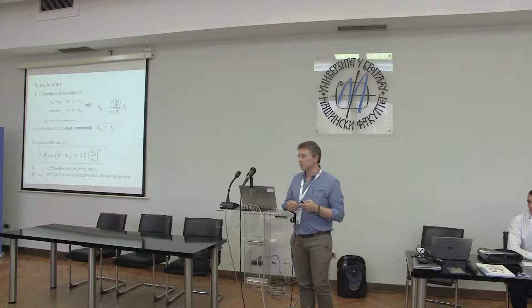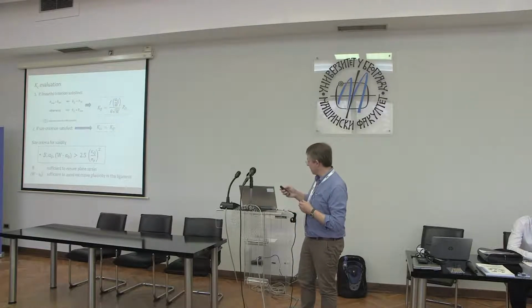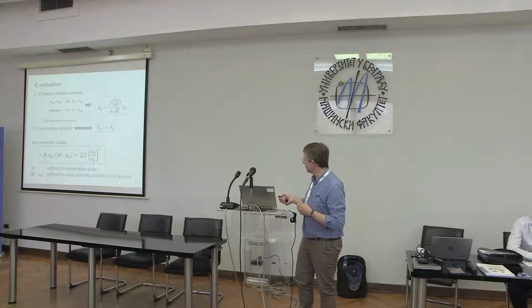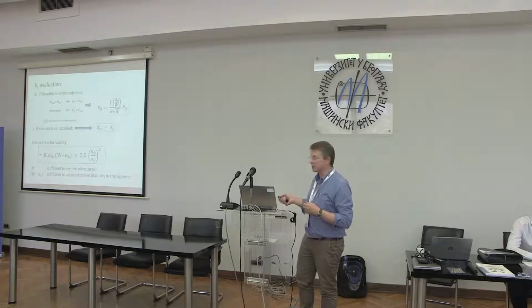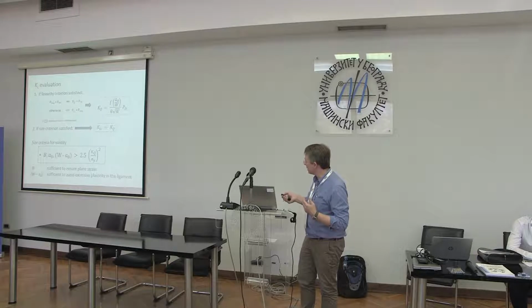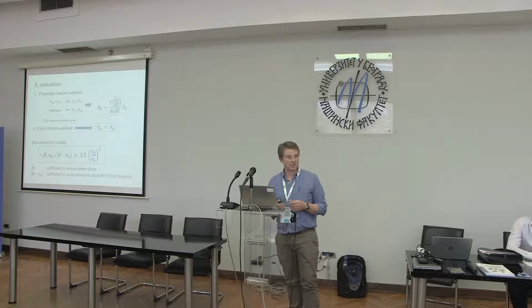What we then do is we compute a provisional value of K based upon our standard fracture mechanics parameters, an analysis using methods that you probably heard described yesterday. We check for a size requirement, and if the size requirement is satisfied, we then call that our K1C value.